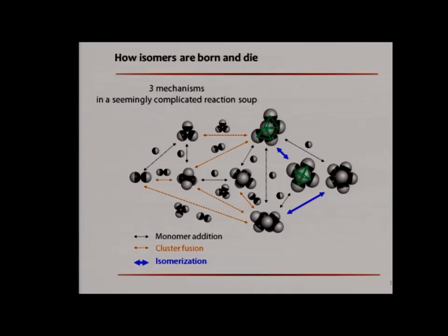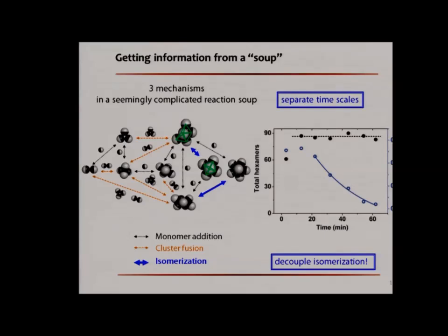It's really just that the isomerization reaction will require both a change in the particle relative orientation, but also a change in the relative positions, like I showed you in the earlier movie. So to me, this really means the isomerization reaction will continue happening even after all the other reactions in the reaction network reach equilibrium. And to me, this really means this separation in the reaction timescales can help us decouple the isomerization reaction from all the other reactions in the reaction network.